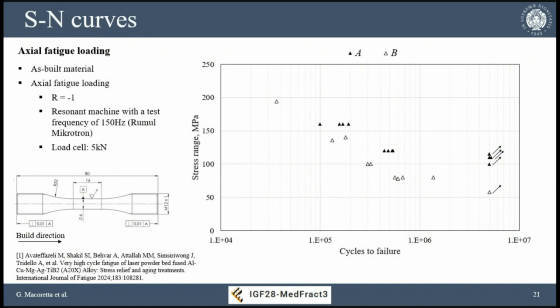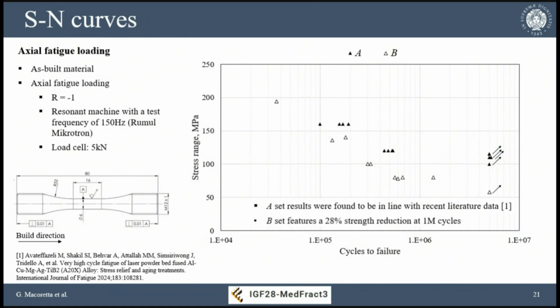Here you can see on the full black triangles the result of the A set, while the hollow triangles show the result of the B set. We can see that the results of the A set are more or less in line with results found in the very recent literature about this alloy. When we move to the B set, we have a decrease in fatigue strength of about 30% if we consider the fitting point at 1 million cycles. This decrease is significant, but much lower than what we experienced in tensile testing and surface roughness increase.